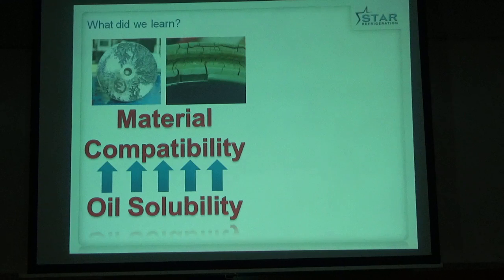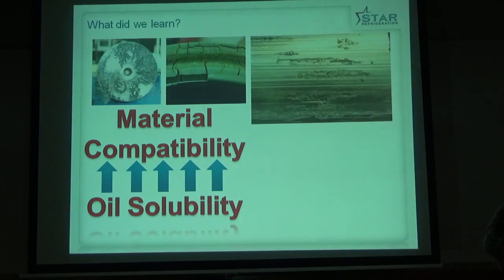This is the resin seal on the bottom of an oil filter which, with the high pressure and temperature, has failed to stand up to the operating conditions, so we've had to look at alternate materials for them. And this is a metal to metal surface from within the compressor where again this oil solubility and cavitation has caused problems on the steel as well as on the aluminium.